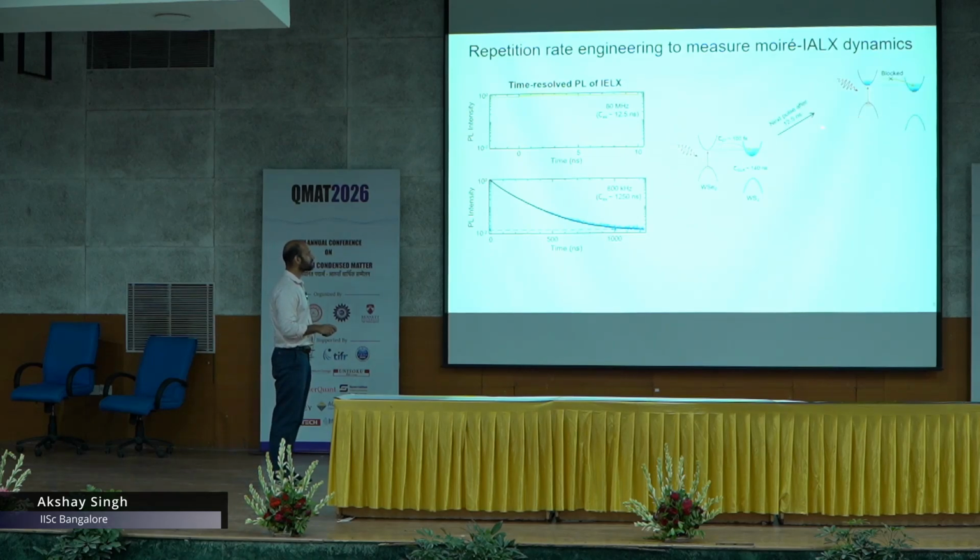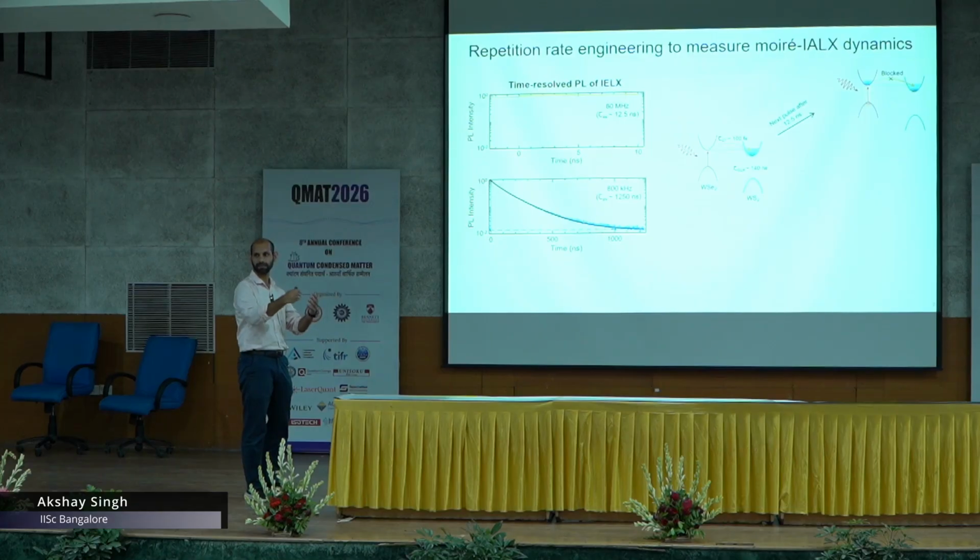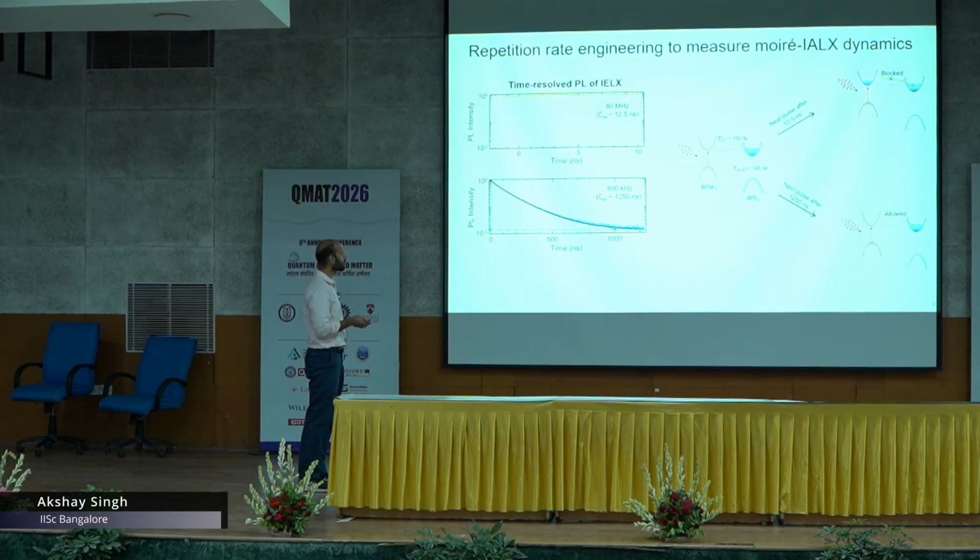We have a pump probe system where the laser pulses come after about 12.5 nanoseconds. So we're not allowing this interlayer exciton system to relax down. We're sort of saturating the system when we are repeatedly pumping it. So it forms this sort of background population of interlayer excitons.